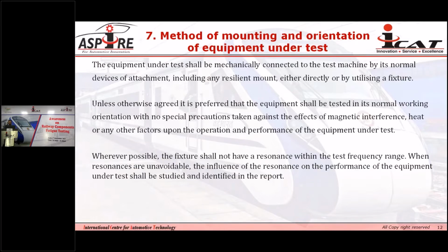Wherever possible, the fixture shall not have a resonance within the test frequency range. When resonances are unavoidable, the influence of the resonance on the performance of equipment under the test shall be studied and identified in the report. So this is the important point. Whenever you use a fixture to mount the components with the test bed, it must be taken care that the fixture should be resonance free in the test frequency band.